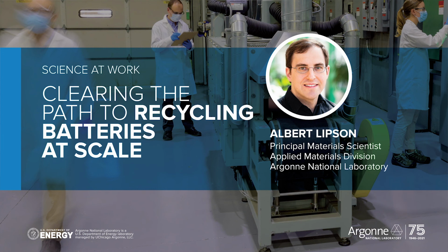And we need to be able to get the electrode materials off of the foils. And we have a number of different methods to do this. There have been some solvent-based methods developed elsewhere in the ReCell Center. And here at Argonne, we're working on thermal-based methods to be able to remove the binder as well as the carbon black that's used to make these electrodes. Once you have the bare powders, you now have a mixture of cathode and anode powder together.